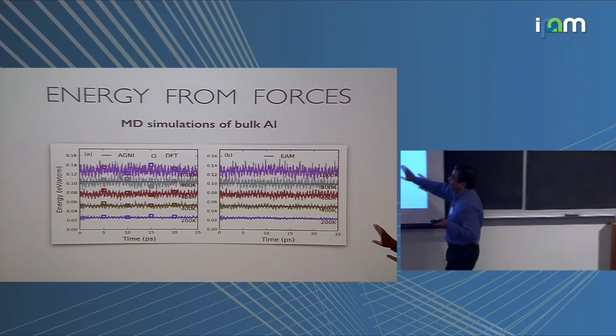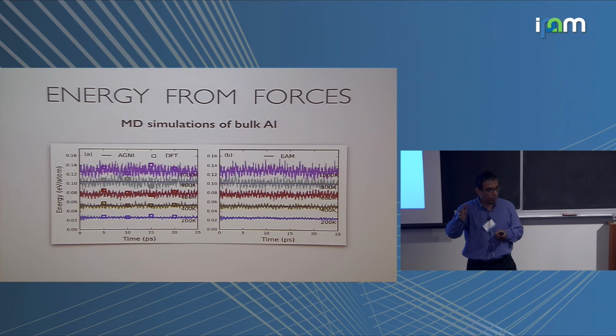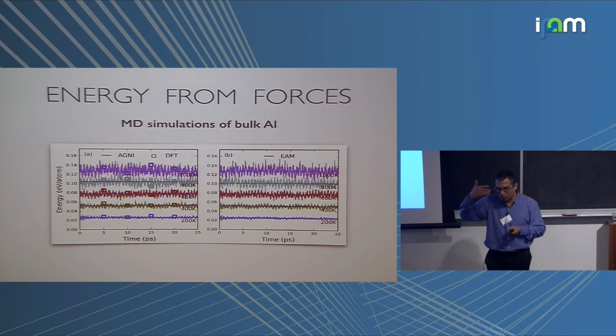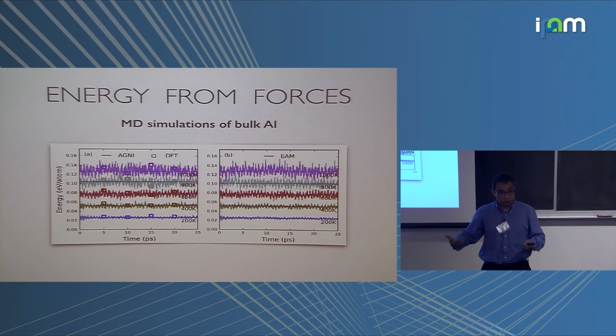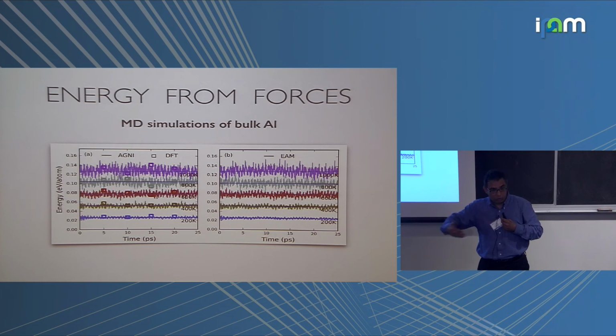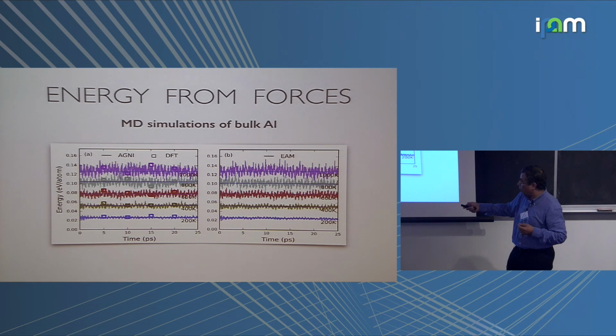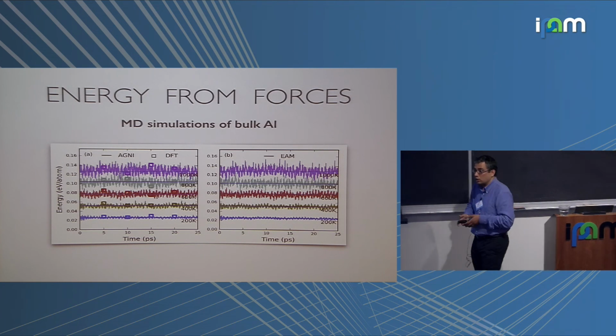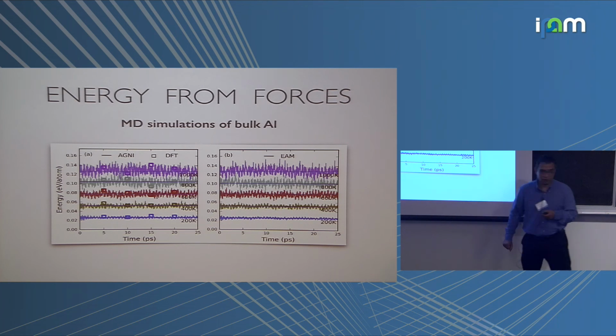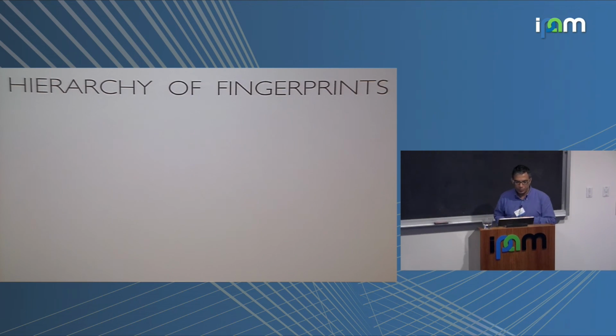One last slide. Energy. Since our force field can predict energies, can we get forces? Since our force field can predict forces, can we get energies out of that? Sure we can. By integrating the forces along the trajectory, we can actually get energies. This is a plot that shows energy predictions from our force field as a function of time for aluminum at various temperatures. These are big aluminum supercells performed at various temperatures, and these blocks that you see are the corresponding DFT calculations, and the energies that we get from force integrations are pretty good. This is the corresponding thing for EAM. I'm going to rush through because I'm really out of time.